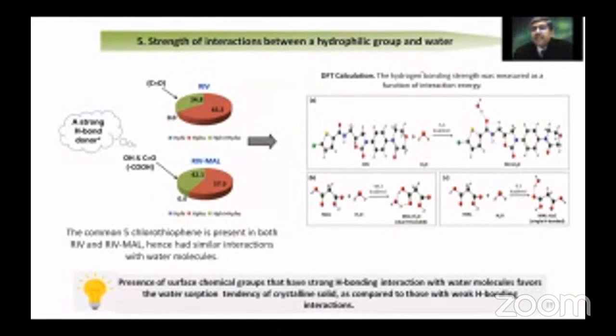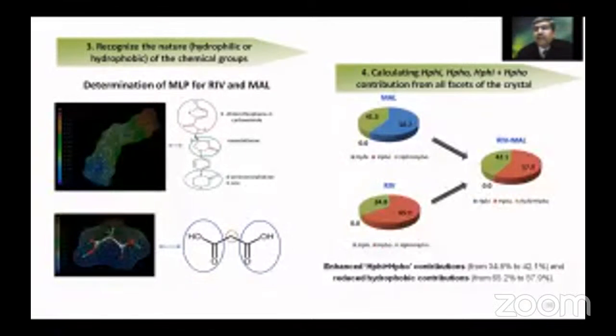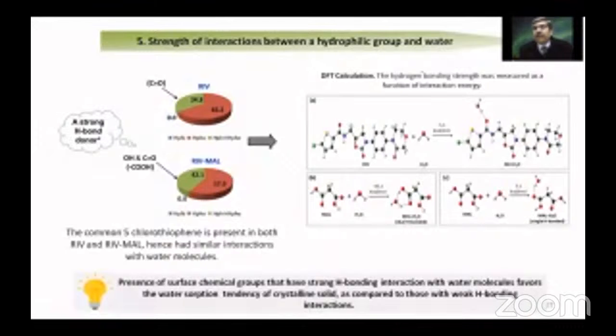However, the difference in the hygroscopicity of rivaroxaban versus the co-crystal was 39 times. And the values that we obtained in the previous case are only marginally different between rivaroxaban and the malonic acid co-crystal. So from 65, it is going to 57, and from 34, it is going to 42. So this does not explain in completeness the molecular reason for the higher hygroscopicity of the co-crystal with malonic acid. We then went on to understand that the strength of the hydrogen bond, or the strength of the interaction between the hydrophilic groups in the co-crystal and water, could be an additional parameter that is contributing to the increased hygroscopicity profile.